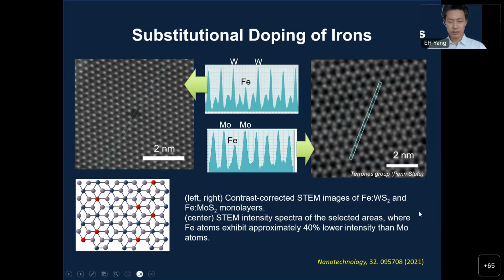So this is scanning transmission electron microscopy, and on the left and right, the images show the contrast-corrected STEM images of this iron doped tungsten disulfide on the left and the iron doped molybdenum disulfide on the right. At the center, you see the STEM intensity spectra of the selected areas, where iron atoms exhibit approximately 40% lower intensity than molybdenum atoms. In this way, you can clearly confirm the substitutional doping, where the iron atoms replace molybdenum or tungsten atoms.